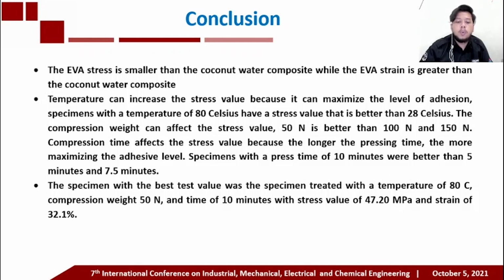The specimen with the best value was the specimen treated with temperature 80 degrees Celsius, compression weight 50 Newton and time 10 minutes, with stress value 47.2 megapascal and strain of 32.1%.